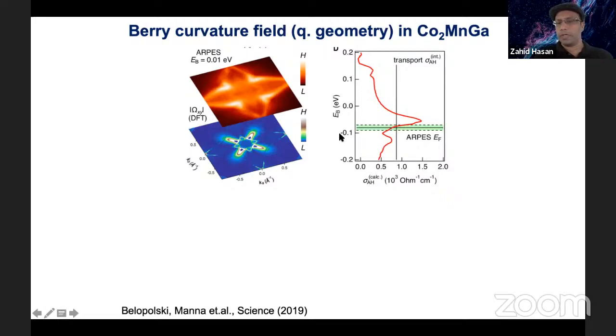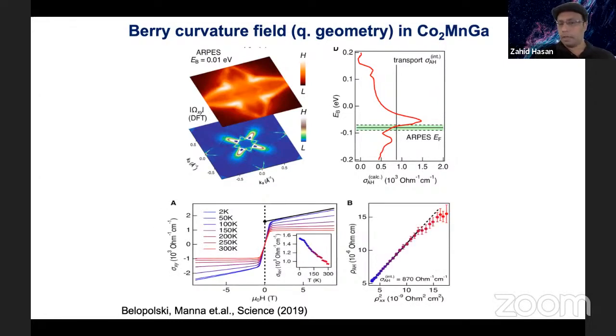We predicted this anomalous Hall effect in this compound. We also know the Fermi level in the real compound, which is an advantage here, since it's difficult to determine that theoretically. So ARPES and DFT together, we predicted that the anomalous Hall conductivity would be about 900 to 1,000 in this compound. And you can see it's away from the singularity: the Fermi level is not very close to the Weyl node where you expect divergence. Then the transport experiments were done afterwards. And indeed, in the anomalous Hall scaling, when you look at rho_AH versus rho_xx squared, you see that this is about 900.